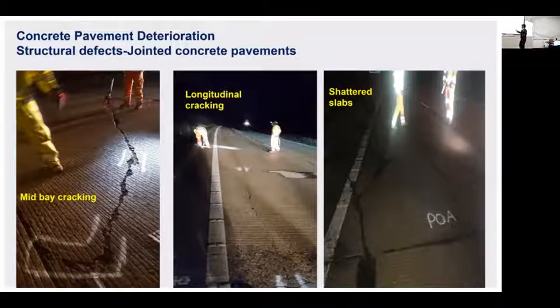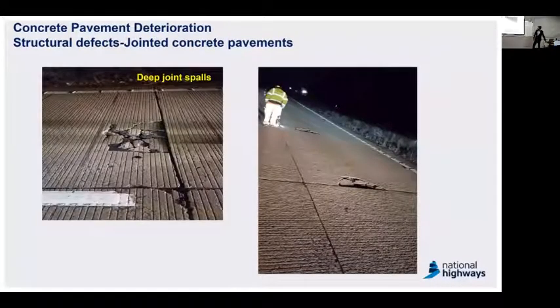We have a longitudinal crack on the near side wheel path. And this one is a shattered slab. And the other one, these are quite common. You can see them at the joint of the concrete pavement. These are big joint spalls. The likely causes for these are possibly issues with the dowel bars, corroded dowel bars, or maybe localized soft spots in the ground on the bearing support.